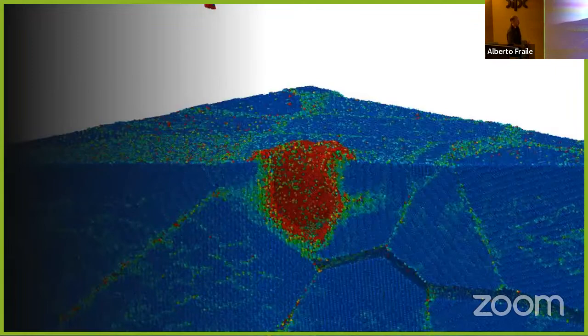go also to more realistic targets, we can also think about polycrystals. So we can make a target that is polycrystalline. We use something called Atomsk. I don't know if you heard about this code. So you can say the number of atoms, the number of crystals that you want in the polycrystal, and you have something with random orientations and everything. Well, in that case, the crater, as you see here, won't be semi-spherical. It will have some asymmetry due to the grain boundaries, for example, here, and you can have much more. You can have also cracks like this, so it's much more complicated.